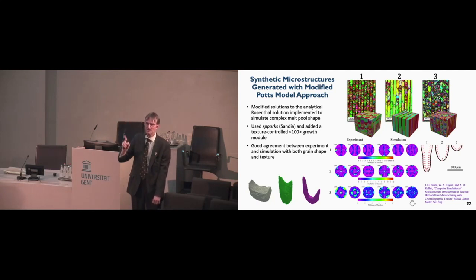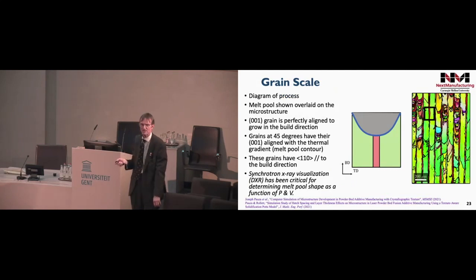And I say that because when I first looked at this, I made the classic mistake of assuming that the long grains were at the edges of the melt pools. They are not. They grow up the centers. And so it's worth looking at, well, how exactly is that happening?